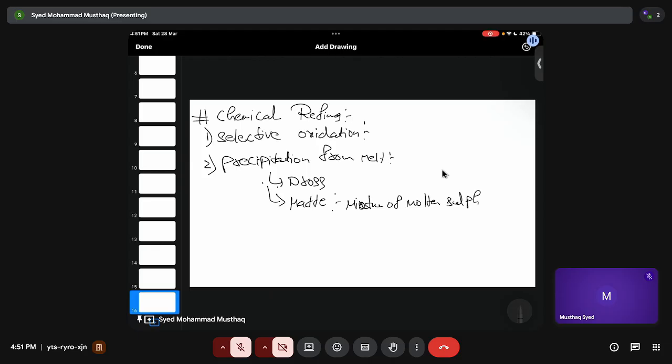What about dross? Dross is a heterogeneous mixture of metals and metal oxides or metal sulfides also. In matte you will find more than 90% of molten sulfides. In slag you will find mostly oxides with traces of sulfides.